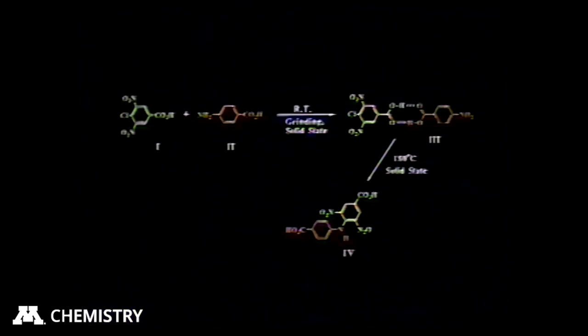We now know the crystal structures of polymorph 3 and of the next polymorph, the higher temperature polymorph. And even knowing those crystal structures, we still could not have anticipated that this reaction would take place, because the crystal structures of the reagents do not mimic a transition state that is reasonable for this product. So there must be enormous molecular motions taking place in order to get this product in the solid state.